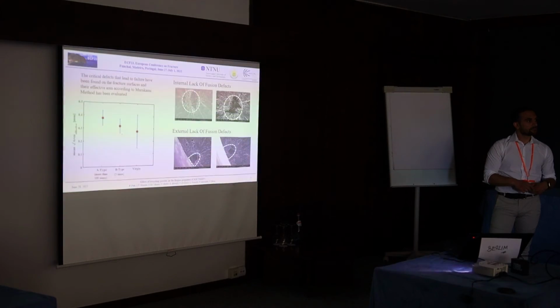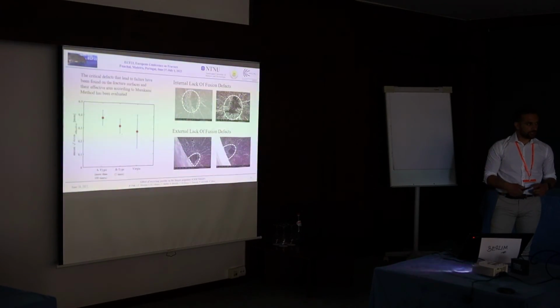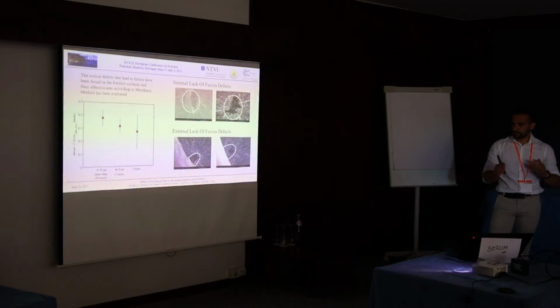Going back to the oxygen content, did you notice a big difference between the amount in virgin powder and that which was recycled 100 times? This was also said by Bellini. The content in the virgin powder, I think, was around 0.12, something like this. I don't remember the percentage exactly, but I can say for sure that for the powder recycled more than 100 times, it was higher than the one suggested by the standard. Yes, during the process there is an oxygen uptake, because even if the process is under vacuum, the oxygen enters. And was this under vacuum or under argon?